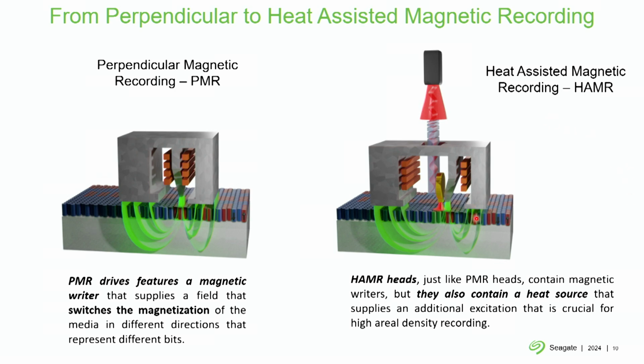Heat-assisted magnetic recording has all those same components. The media is still magnetized up or down relative to the plane of the disk. There's still a magnetic writer that supplies the excitation needed to switch the magnetization of these media grains. But there's an added element. It's a thermal excitation that aids in the switching process for this new media that we need in order to keep increasing the areal density.